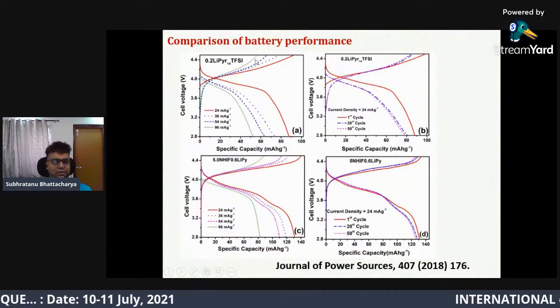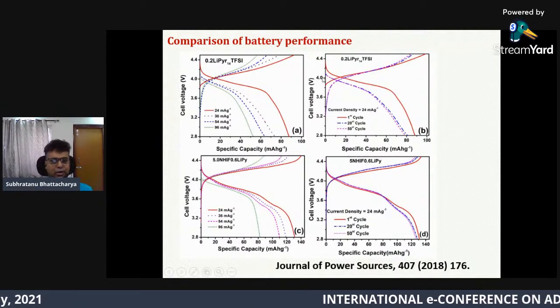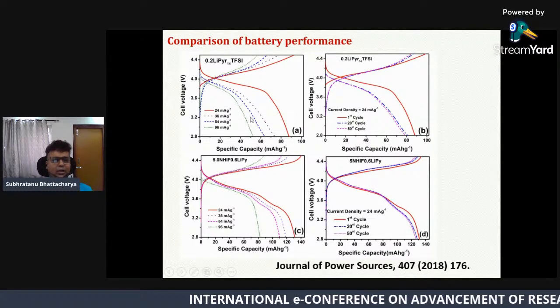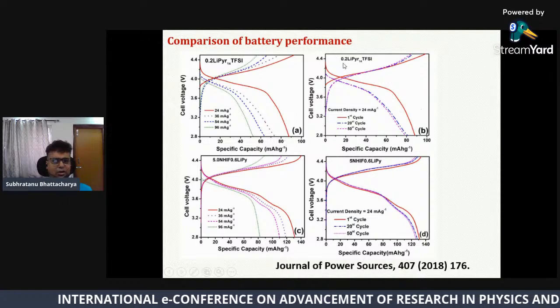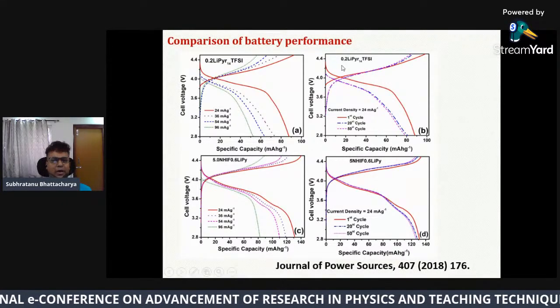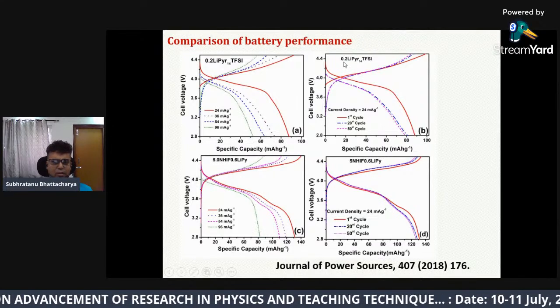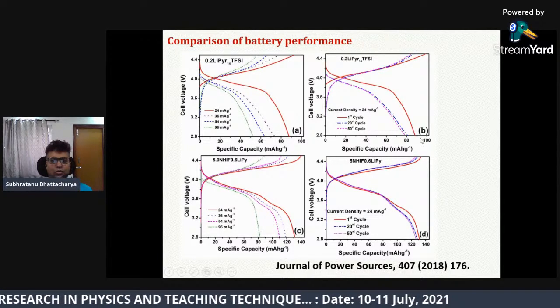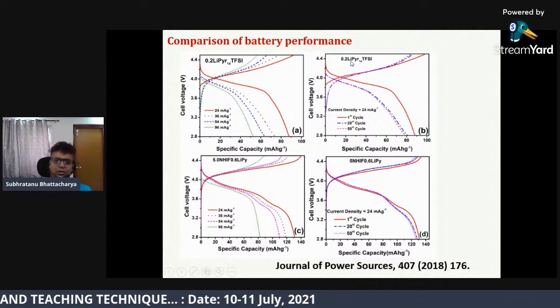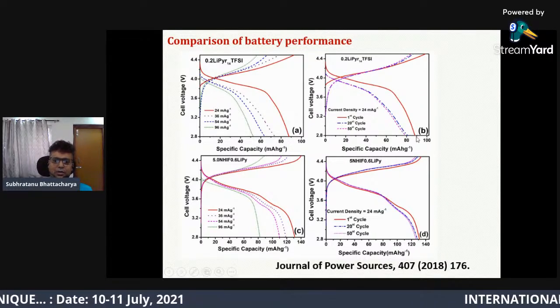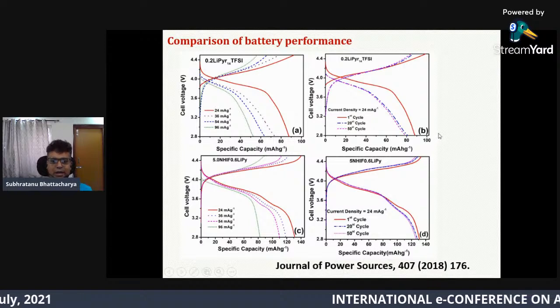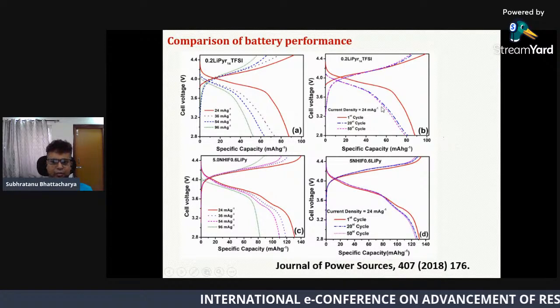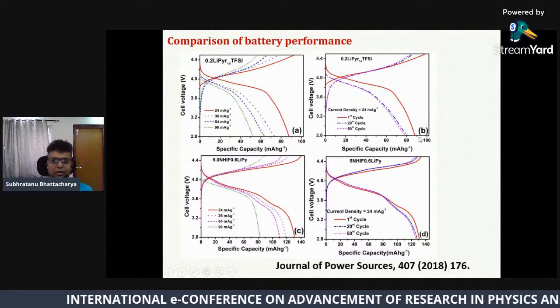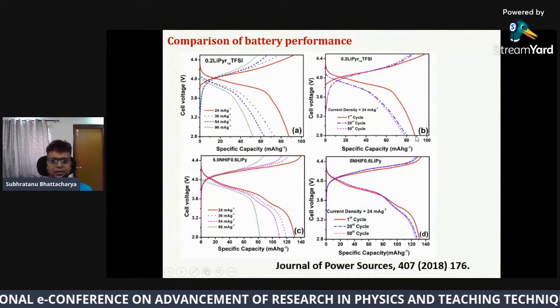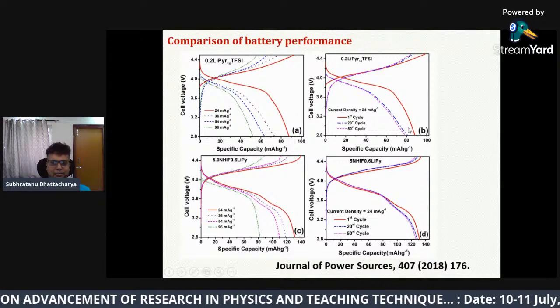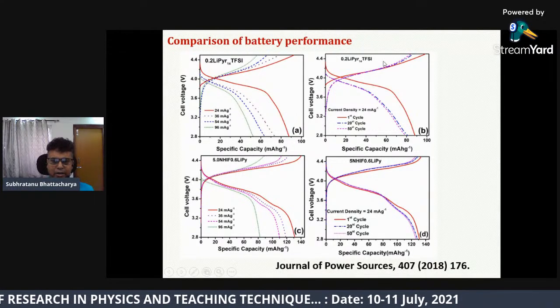You can see these are the battery performances. I don't know whether you can understand it or not. These are normal ionic liquid based electrolytes. You can see only 0.2% lithium salt can be added in that. Since the salt concentration is very low, the battery performance is also very poor. The theoretical capacity is around 140 for this particular cathode, but only 90 mAh could be achieved for the normal ionic liquid based electrolyte.